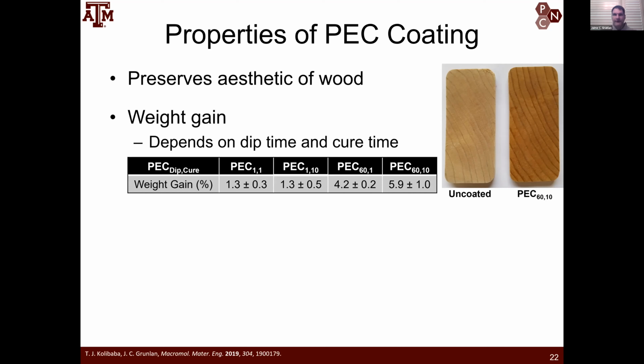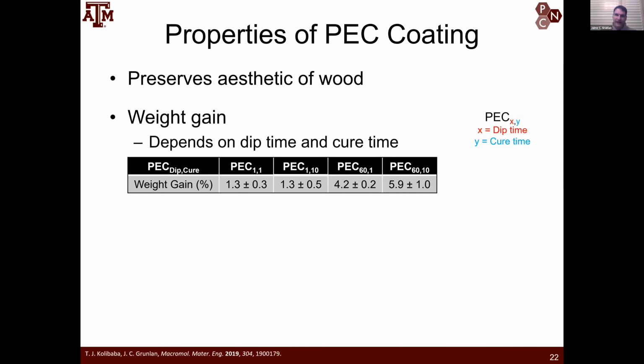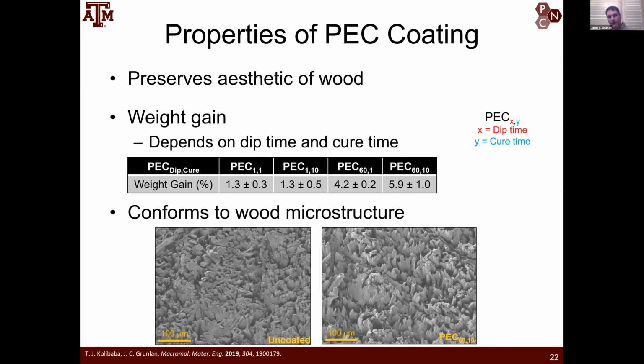And then we can see the weight gain of various dipping times and curing times. That means the amount of time in the polyelectrolyte complex and the amount of time in the buffer solution. I should mention, if you were to use pressure treatment or modern wood processing treatments, you could actually dramatically reduce these times. These are long times because we are doing it in a laboratory without wood processing equipment. This is just proof of concept. But anyway, if you look at wood after coating, you don't see any difference in terms of the nano microstructure.